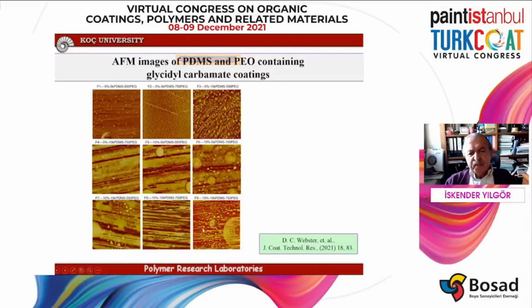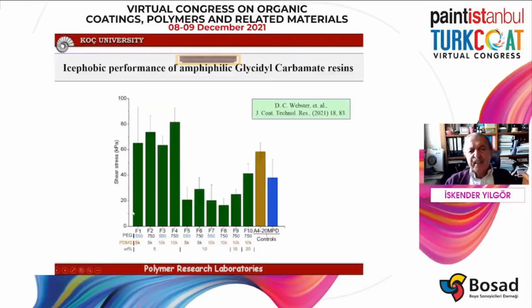Here, the lighter parts are silicone. As you can see, as you increase the silicone, the surface changes dramatically. And then they looked at the ice adhesion strength. As you can see in some formulations, especially where they used 10,000 molecular weight silicone and 750 molecular weight PEO, around 10% each, they obtained the lowest result, which was around 15 kilopascals. So this was pretty good. But depending on the composition, again, you can look at this paper in this reference.